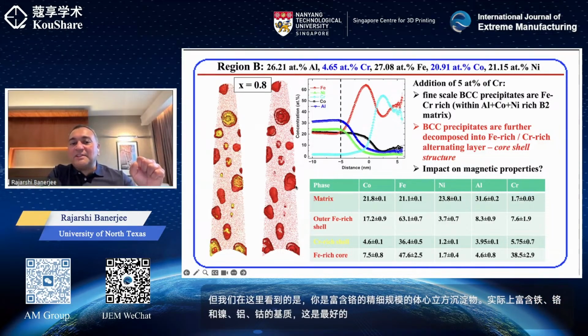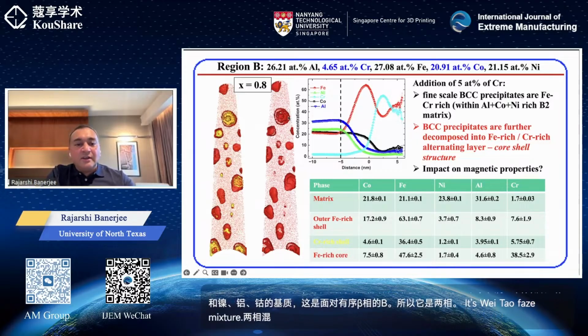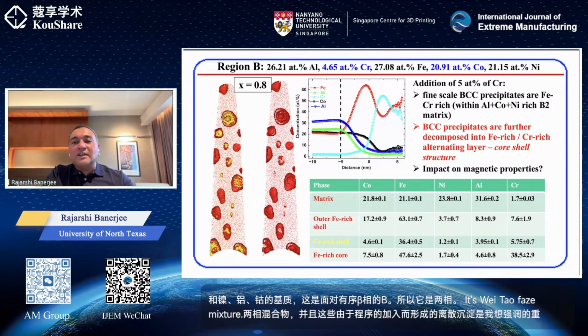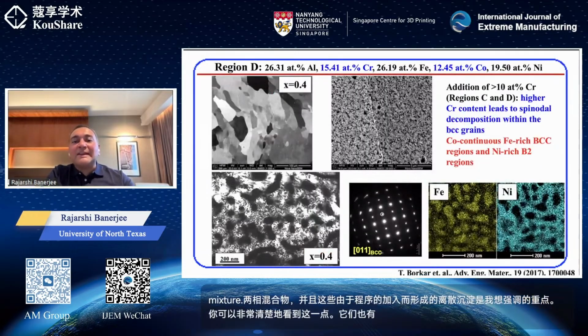And these discrete precipitates are forming due to the addition of the chromium, is the point I wanted to highlight. And you can see that very clearly. They also have a core shell structure and so on. Very interesting microstructure, not just from a structure point of view, but also magnetism. And I'll get to the magnetism in a minute.